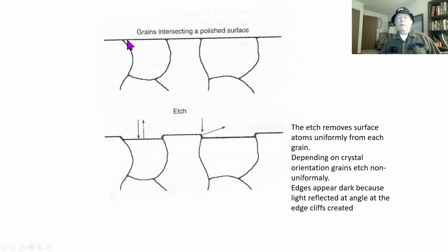After polishing the surface flat and etching, the nital etch will etch the various grains differently depending on the orientation of the lattice. Some will etch faster and become more deeply etched than others. In an optical microscope, your eye is up here, and the light's being reflected back at you. So in this flat region, everything's white. However, at these edges, you can see the light gets reflected off the side and they look dark. That's why you see them in the optical microscope.